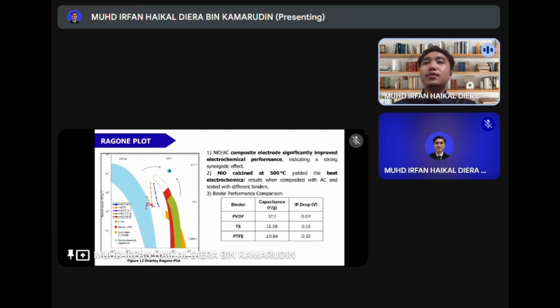PTFE again shows the lowest performance in both energy and power density. The plot also emphasizes the role of the NiO-AC composite, where NiO enhances performance across all binders, and NiO calcined at 500 degrees Celsius gives the best results, making it the ideal condition.